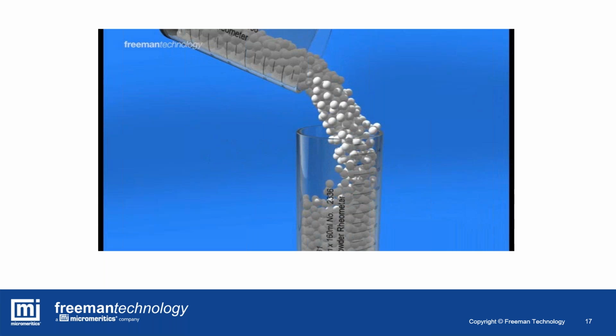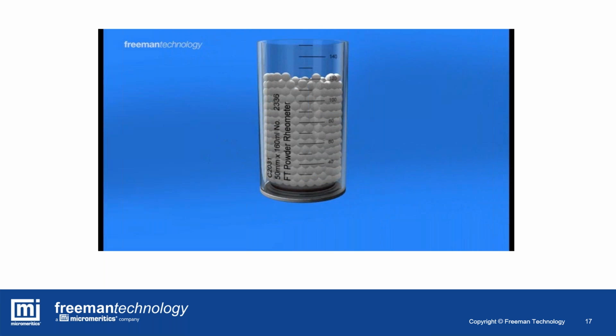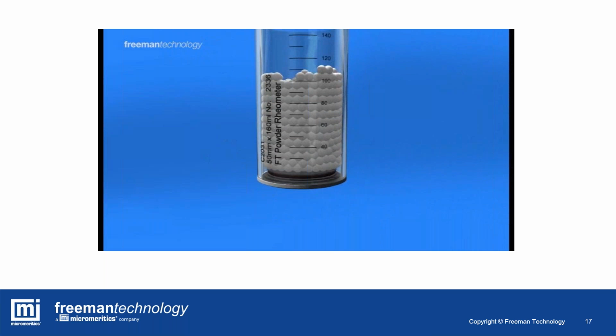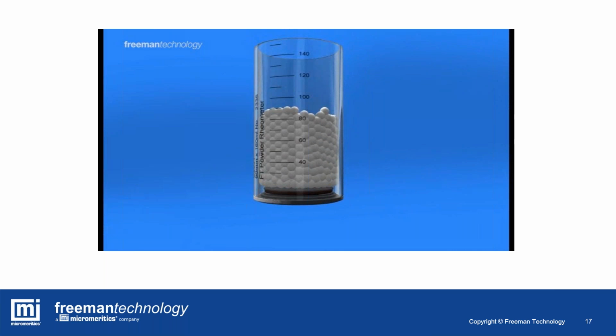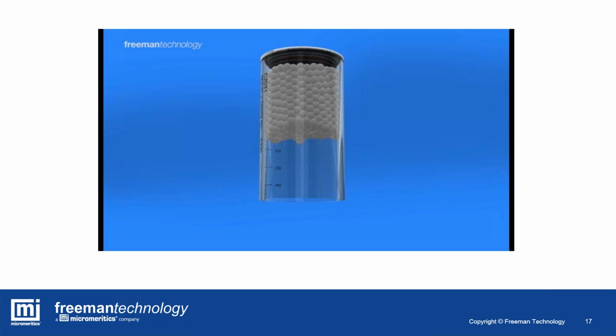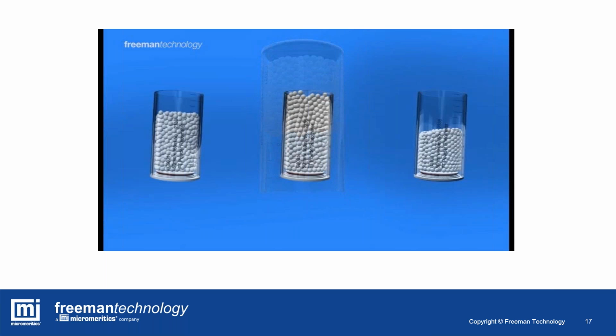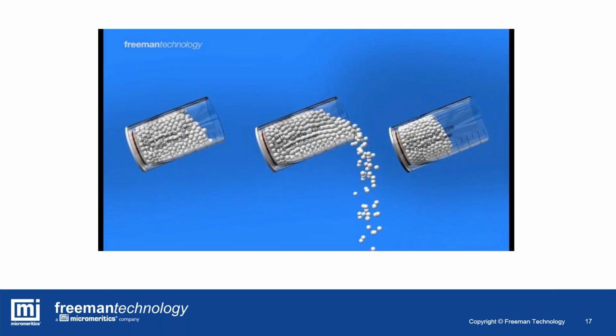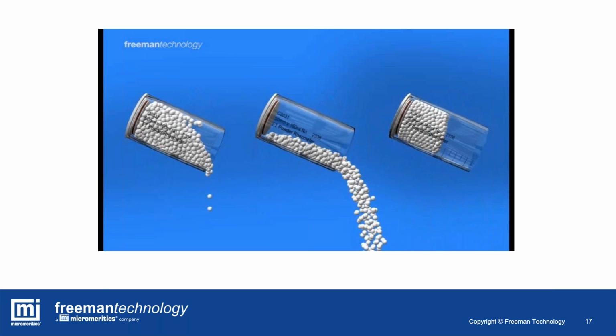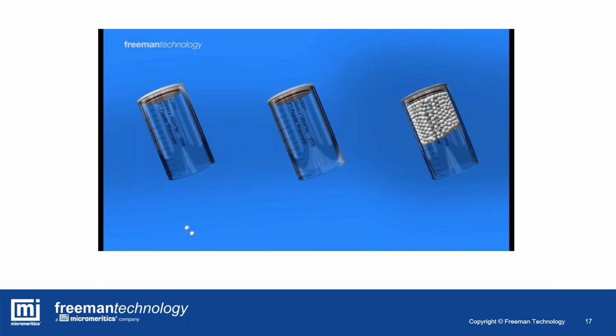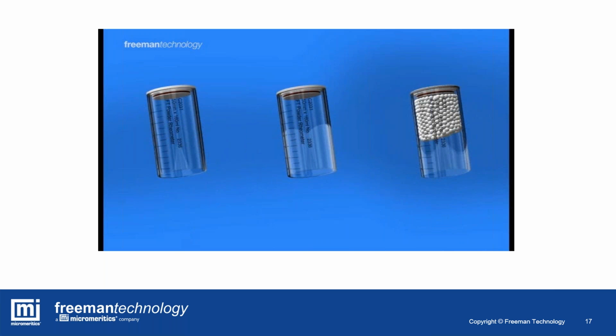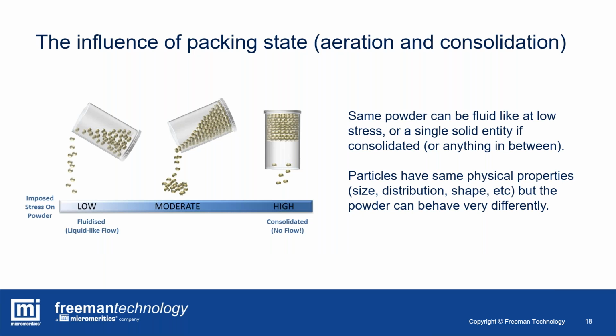But if you take that same collection of particles and you vibrate or you consolidate it, the gas, that phase, is extruded from the powder bed, and you get a totally different interaction between those particles. So depending on the stress conditions, you can have a fluid-like response like the one in the center here, an intermediate type flow, or no flow at all. And the interesting thing about that is that the same powder can flow like a liquid at low stress, or behave like a single solid entity if it's consolidated.